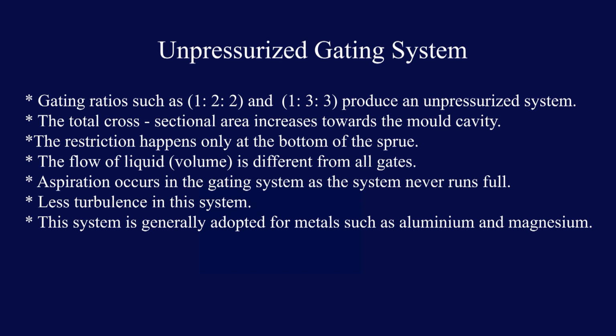In an unpressurized gating system, gating ratios such as 1:2:2 and 1:3:3 produce an unpressurized system. The total cross-sectional area increases towards the mold cavity. The restriction happens only at the bottom of the sprue. The flow of liquid is different from all the gates. Aspiration occurs in the gating system as the system never runs full. There is less turbulence in the system, and this system is generally adopted for metals such as aluminum and magnesium.